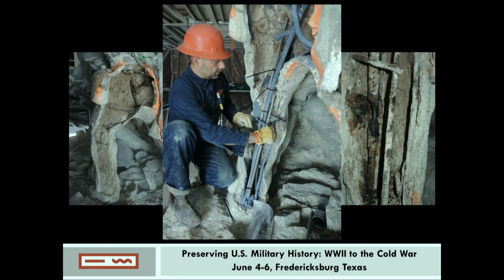Corroded rebar armature was removed with a metal cutting wheel and replaced with new fiberglass rebar of the same approximate diameter. We used number 3, 4, and 5 rebar rods, and I've given the measurements of those in the paper for those who are interested. The new rebar were lapped onto existing rebar with nylon zip ties, and you can see Paul doing that here in this image. Where the rebar were in direct contact with the concrete shell, they were secured to the shell with a structural epoxy.